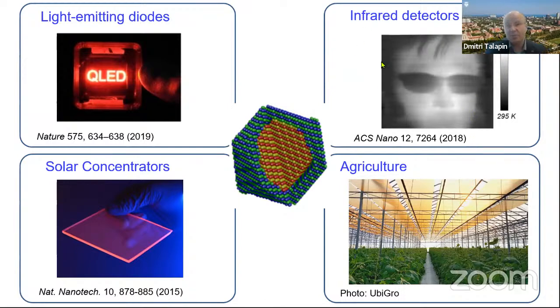The other area where these materials can be very interesting is infrared and near-infrared detectors, where you can make your inexpensive CCD camera sensitive, or CMOS camera chip sensitive, to infrared. And there is a lot of interest from smartphone manufacturers for this. There is a lot of interest within the energy technology domain, solar concentrators, solar cells, and even agriculture. It turned out that these materials are potentially very interesting for agricultural applications. And the idea is the following. Leaves are green because chlorophyll has an absorption band in the orange-red part of the spectrum, and they have an absorption dip in the green.